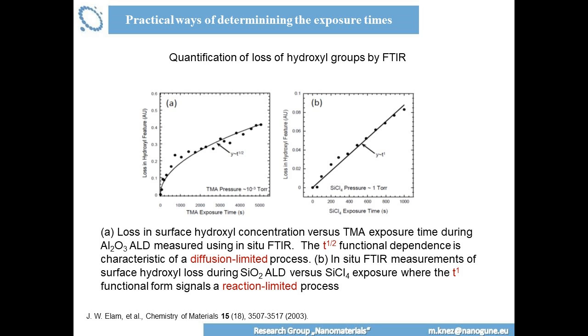So here you can say that this is diffusion limited, and this is reaction limited. Means here the reaction is much slower than the diffusion, so you don't really need to care about the exposure time because you need to enhance the time anyway for the reaction. It's slower. But if you have this kind of reactivity here, it means this is a fast reaction, and your process, the coating of any pore or structure, is purely limited by the diffusion of the molecules. So here it's physics and here it's chemistry.